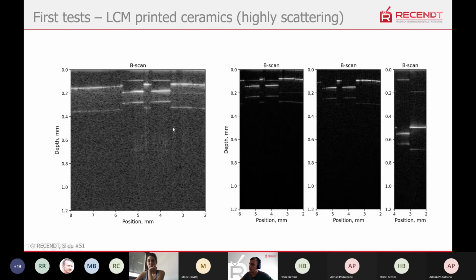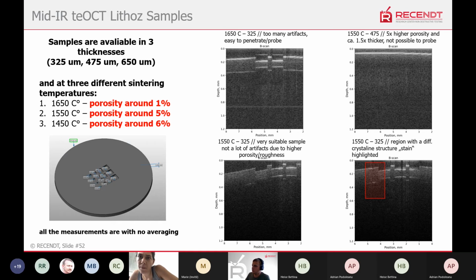Yeah, just some first results for ceramic samples, and these are 3D printed samples, and I have to mention that they are very scattering. They are a lot more scattering than what Rongsu simulated and gave me, because surface scattering is also strong here. They are very rough. Yeah, and it worked quite well here. Also for higher porosities of around 5%, but already not so effective as for lower porosities. We have various test samples of different structures and sequences to test.